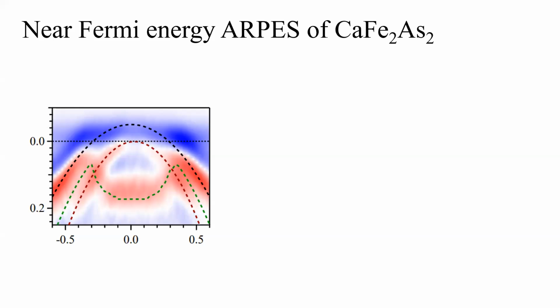Of course we require electronic structure calculations from DFT, but we also do one thing: we draw EDCs and MDCs. MDCs are the momentum distribution curves at different binding energy values. Even if you are not able to see a band, as in this case where you can't see a band here, if you draw an EDC you will see a small feature at those positions, and those features will move with the binding energy value. By fitting those features, we draw these curves. But of course, we also compare these things with the theoretically calculated electronic structure. Otherwise, it is very difficult to find the position of the bands or the number of bands itself.